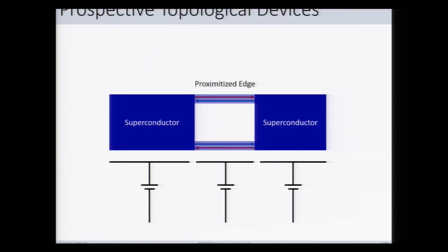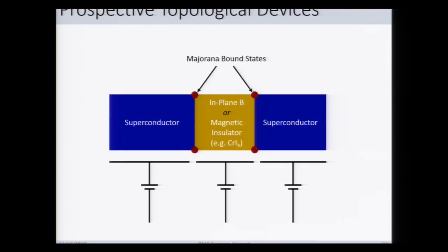So we hope to have a Josephson junction with these helical edge modes defined in the same material simply by gate voltages. And beyond this, we already know that magnetic fields will gap the edge modes. And 2D superconductors with strong spin-orbit coupling are known to be relatively insensitive to in-plane magnetic fields.